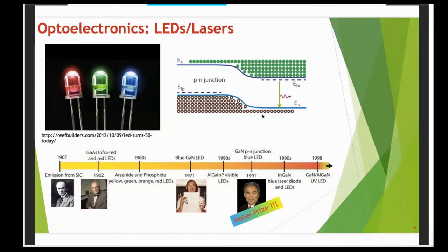And this work led to the field of nitride LEDs. So GaN PN junction LEDs became indium gallium nitride laser diodes and LEDs, and it was only a matter of time when we would venture into the ultraviolet regime with these materials, because nitrides are high band gap materials, the gallium nitride and AlGaN compounds. So you can get practically from 210 nanometers to 400 nanometers of emission from these materials.